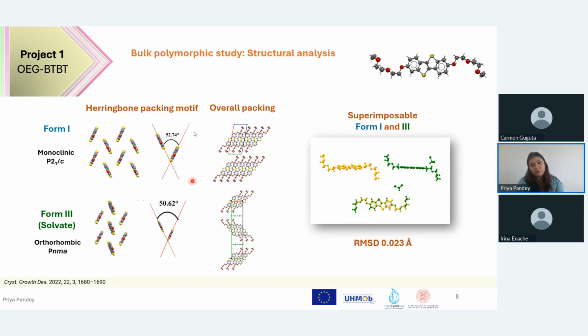And if we look at the overall packing, we can see they are forming layers. In form 1, they form parallel layers, while in form 3, they form anti-parallel layers with solvent molecules intercalated between them. So despite some differences, we found that both these polymorphs are actually quite superimposable.